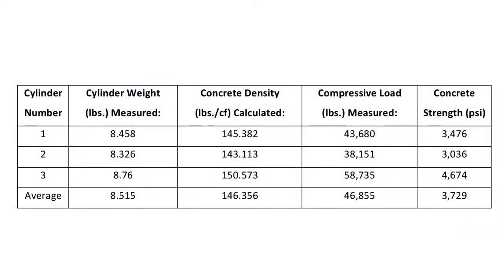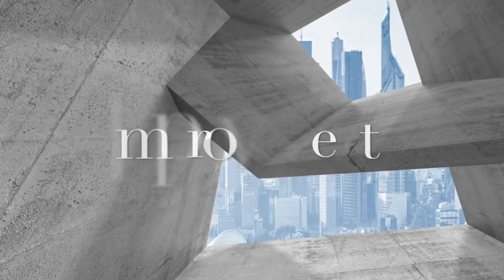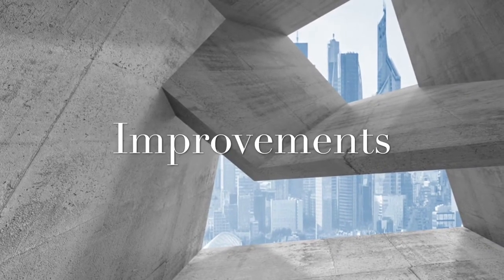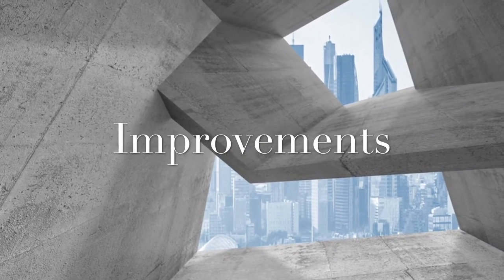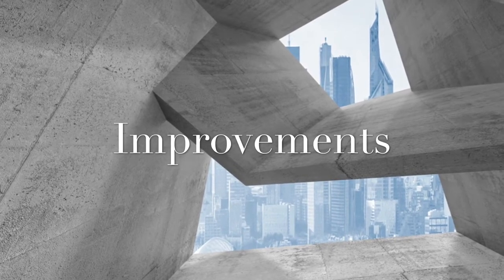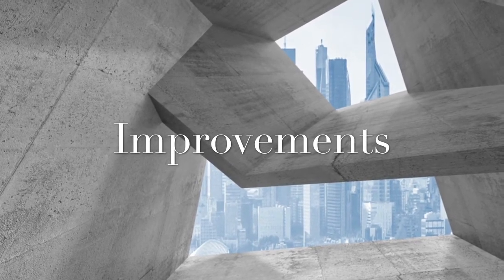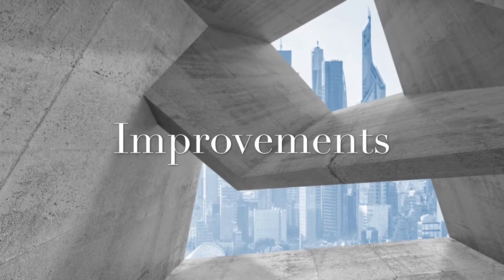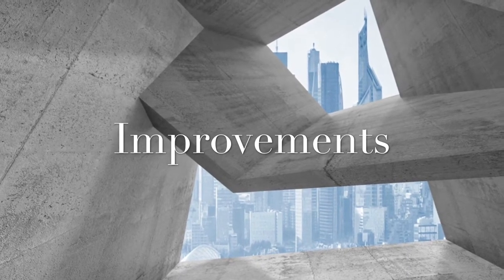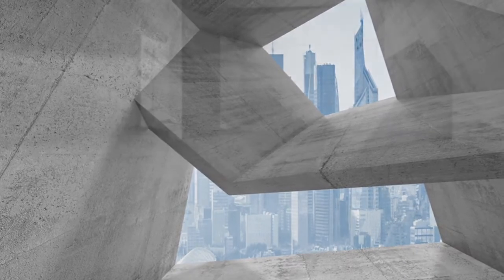As seen here, the density directly relates to concrete strength. Thus, by filling the pore spaces of our cylinders and creating more uniform concrete, our strength would increase and potentially hit that 6,000 psi threshold. We meant well with the use of coarse aggregate, but by overdoing it, we left our concrete prone to fracture. Areas where other groups edged us out was by using less large aggregate, having a more workable mix with a slightly higher water-cement ratio and a little more plasticizer, and by having 2 attempts at their mix.